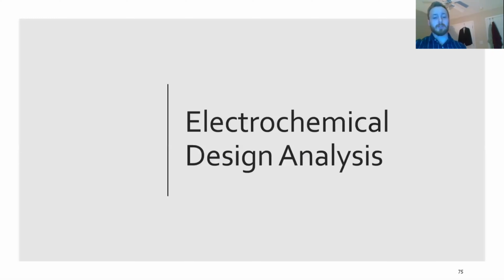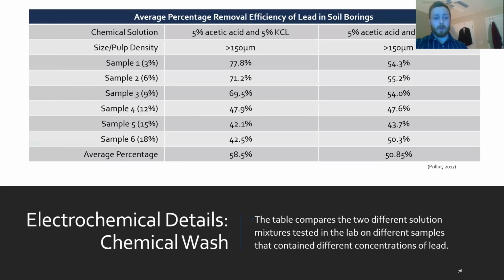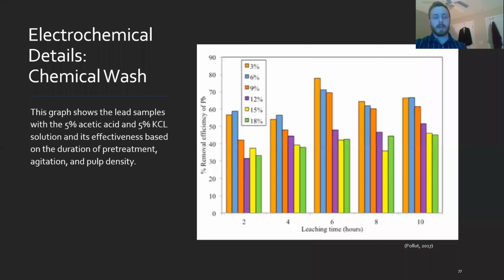Up next will be our electrochemical design analysis based off of our laboratory studies. So for the chemical wash portion of this process, we compared 5% acetic acid in KCl solution with 5% acetic acid and 10% KCl solution. As you can see here on the table, the highest average percentage reduction is 58.5% with the 5% acetic acid and KCl solutions. Here's a graphical representation based off the different pulp densities, of which the 3% pulp density had the highest removal with the 5% acetic acid and KCl solution.